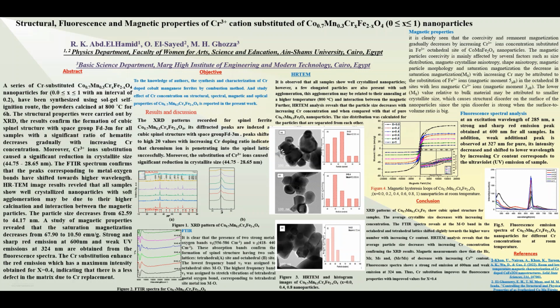From the high resolution transmission electron microscope results, it is clear that all samples crystallize in nanoparticles with soft agglomeration, which may be due to higher calcination temperature and magnetic particles. It is also observed that the particle size decreased from 62.5 to 44.17 nanometers, which is in good accordance with the XRD result.